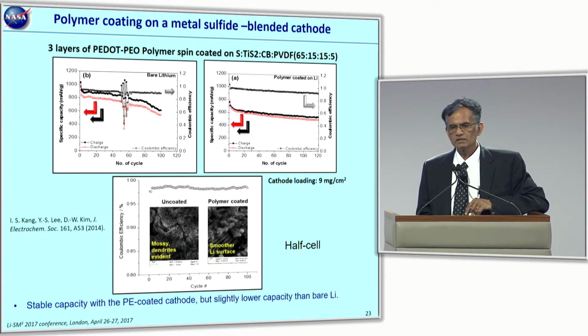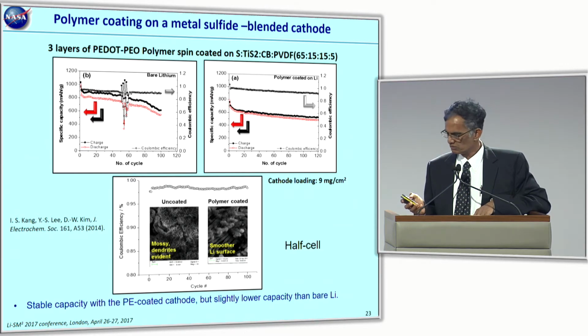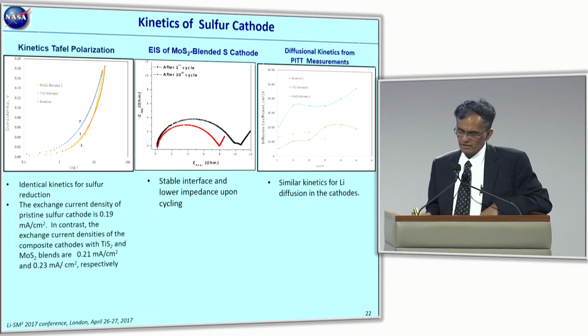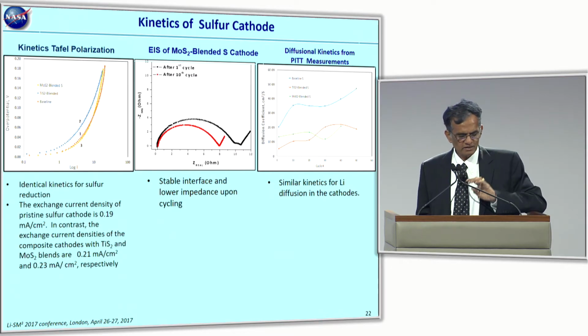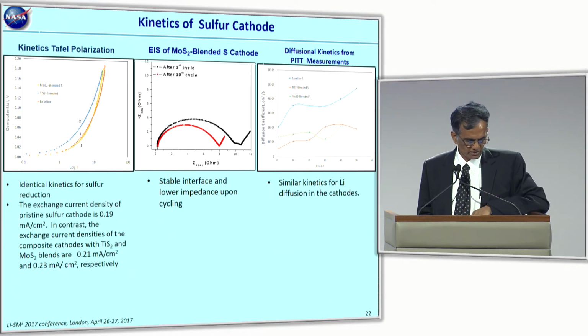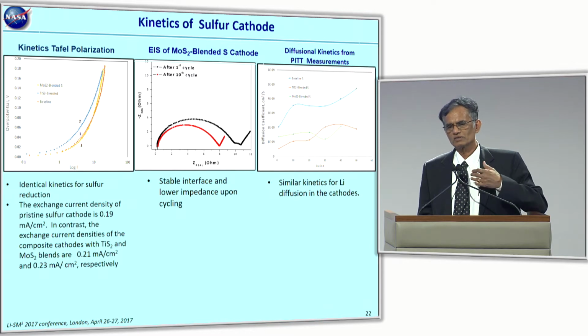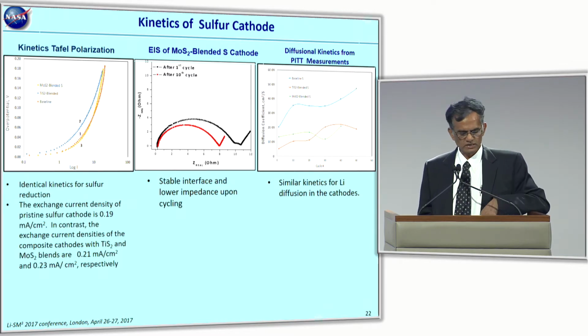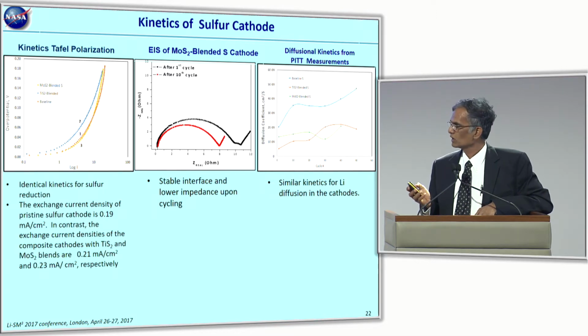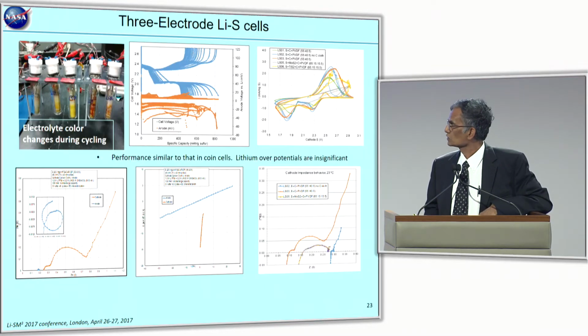On the right, you can see the same cathode, but with an anode which is protected with this polymer, and you can see a more stable capacity. We are still trying to optimize the number of layers that we need. And moving on, we looked at the kinetics, what this metal sulfide actually does. It looks like both the charge transfer and the diffusional kinetics seem to be the same with this metal sulfide, much like what we would see for the baseline sulfur cathode.